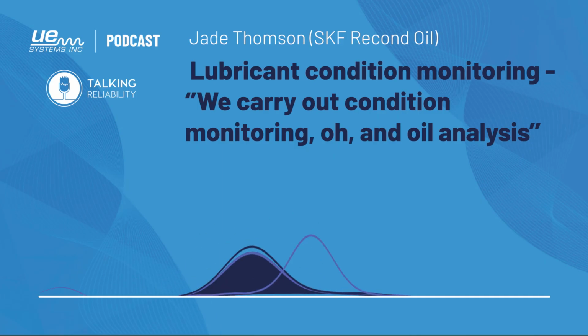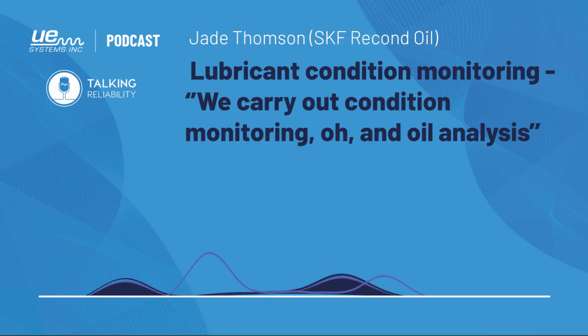On the left, we've got, hopefully everyone's got maybe a generator or an engine on site. On the left, we've got a trend of what we call TBN and TAN. And this is additive versus acid. This is an environment where quite frequently the oil has to be changed, and it's just a way of trending that crossover and how soon it needs to be changed. Again, it is just a routine form of oil analysis, but it's very important we're doing it quite frequently.